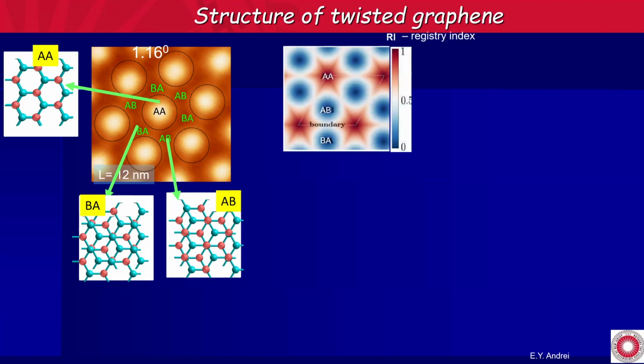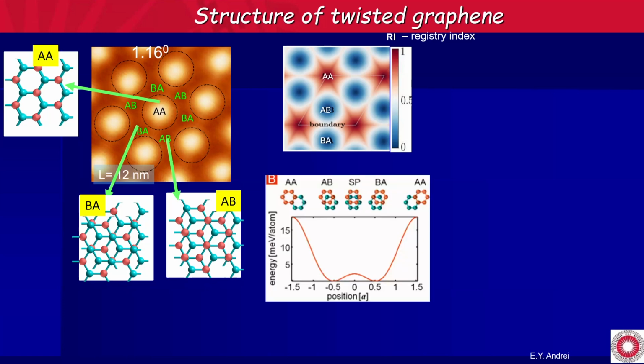Now, when you do a little calculation, you calculate the registry index, which gives you the ratio of the areas of the bright and dark regions. You see that the AA and the AB and BA take up about the same area. And it doesn't matter the twist angle. No matter what the twist angle is, they always take up the same area. But in fact, there is some energetics that goes on here. And it turns out that the AA configuration is extremely expensive. It's about 20 millielectronvolts per atom that you have to pay to have an AA configuration. AB and BA are much cheaper. This is the Bernal stacking, and this is the saddle point here.